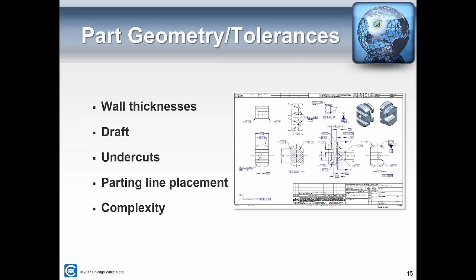Undercuts are something that could potentially be done with other casting processes, but in general are not common in die casting applications. Parting line placement: we can talk about what gate and vestige remnants you'll see on the parting line, and also where to advantageously place your parting line so you can get the best fill possible and allow air to escape the part as efficiently as possible. And then there's the general complexity of the part. Sometimes it makes sense from a die casting standpoint to fit 3 pieces into one piece. We cast away, and I've reduced the number of SKUs that I have for an assembly. But if the one-piece application comes across the quote desk and we see that it needs 4 slides, we may recommend splitting that into 2 parts. We can help you with that process, and we often see it makes for a more efficient assembly and a lower total cost, if you want to look at it that way.